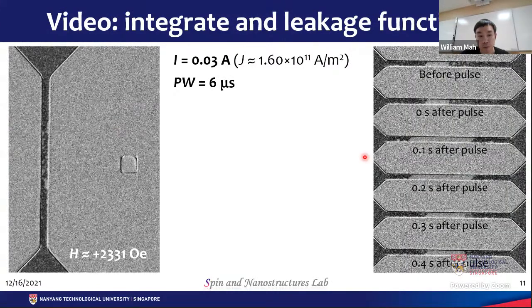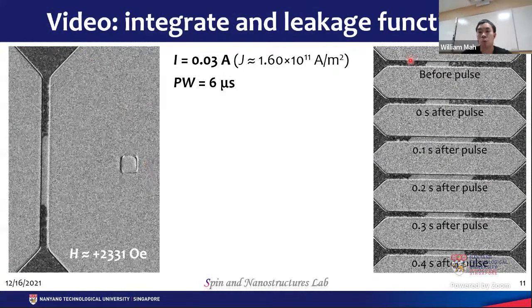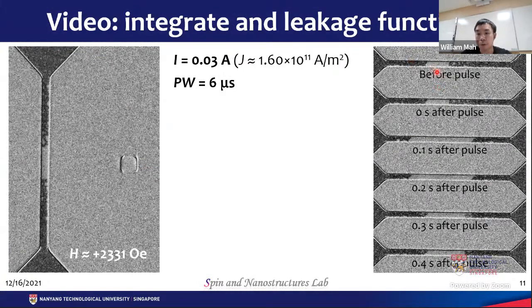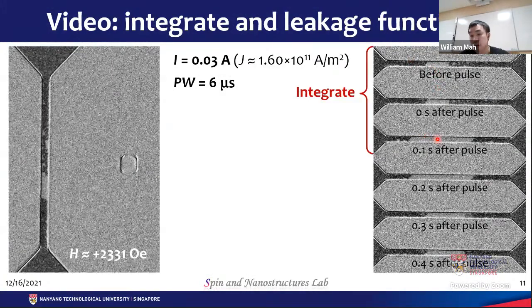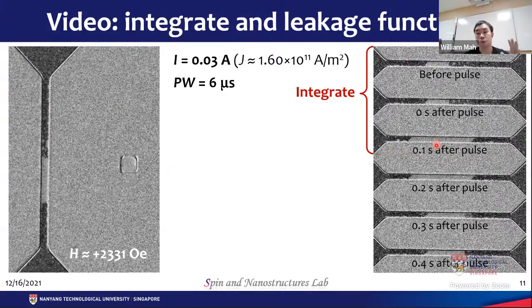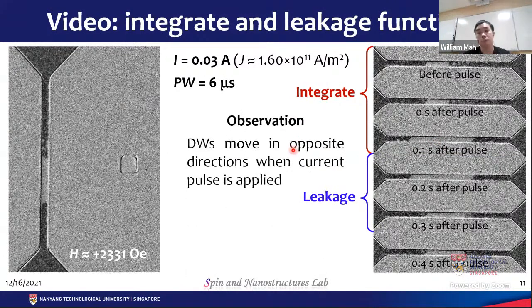So these are the screenshots from this video. When I apply a current pulse, the domain walls get pushed back, which is the integrate function. After a short amount of time, the domain walls come back. That is the leakage function. But one interesting observation is that the domain walls actually move in opposite directions, which is not indicative of the spin transfer torque effect. Because if spin transfer torque is dominant, then the domain walls would move in tandem. But in this case, the domain walls are moving in opposite directions.